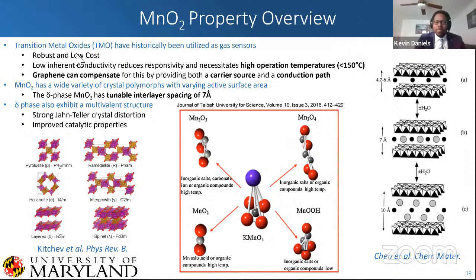But the material is robust and relatively low cost. So the question is, can graphene compensate for this by being a carrier source and a conduction path for carriers coming from our transition metal oxide? Now, the difficulty is manganese dioxide has a wide variety of polymorphs with varying active surface areas, but we're really interested in this layered structure. And being able to get this delta phase layered structure is actually pretty difficult.